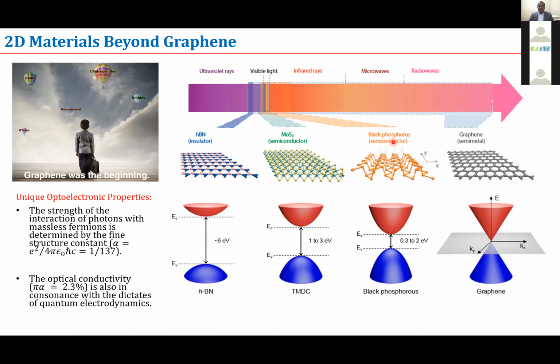There are other materials like phosphorene or black phosphorus, whose band gap is 0.3 to 2 electron volts, that also corresponds to visible and some part of the infrared light. So now we can also think about how we can use these materials individually. If you talk about boron nitride, it's only active in the UV light. It can be useful for a UV detector. It can combine with the transition metal dichalcogenides, which respond to the visible part of the light. That way, we can do a lot of permutations or combinations. We can combine these materials to create the desired structures or devices.